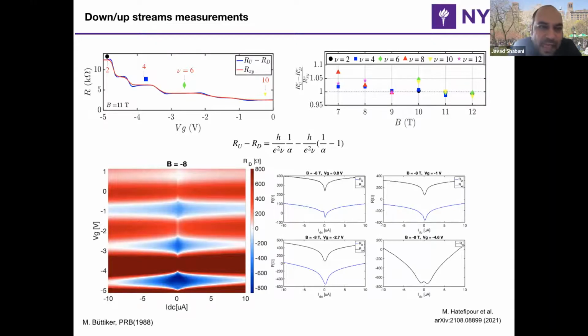And if you look at the top left, you would see that the RXY data is red. Previously, RU was below the red graph, if you remember. Now that I subtract that negative resistance from the downstream, you see that exactly at the quantum Hall values, the red and blue match up, while when you are not in a quantum Hall effect, they deviate, which is fine, because this picture is only true when you are in the Hall regime. And you can try to plot that as a function of field, and you see within some error bars, basically we recover 1 if we ratio this subtraction to RXY in quantum Hall effect, right? So that is very reassuring that there is no funny business going on between upstream and downstream.